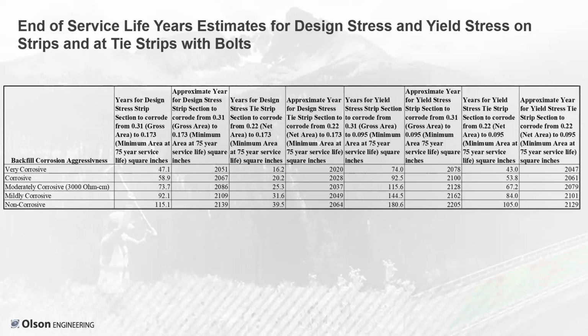As indicated earlier, based on the resistivity values, of very corrosive to moderately corrosive, in this case, cutting it off at 3,000 ohm centimeters, in other words, below that, and mildly corrosive as it got higher to non-corrosive. And that would be 5,000 ohm centimeters and even higher at non-corrosive. So the calculation then says, if we look at the first column, the years, second column over, for the design